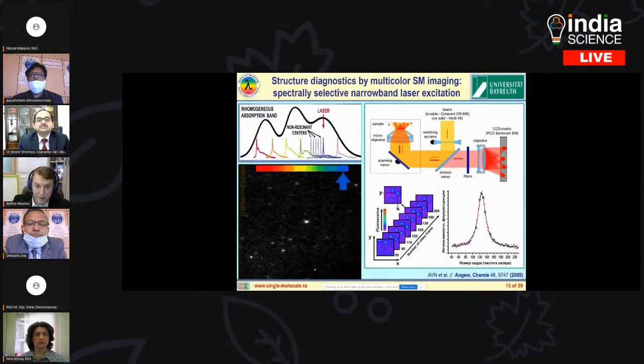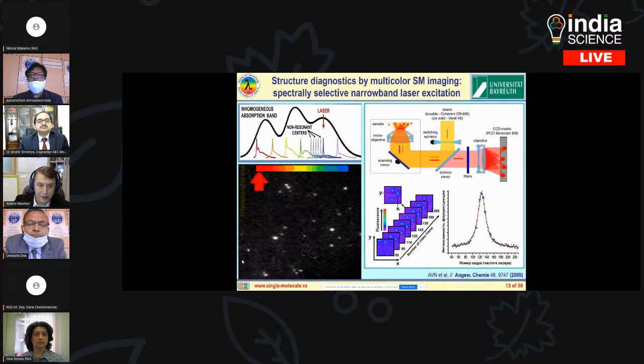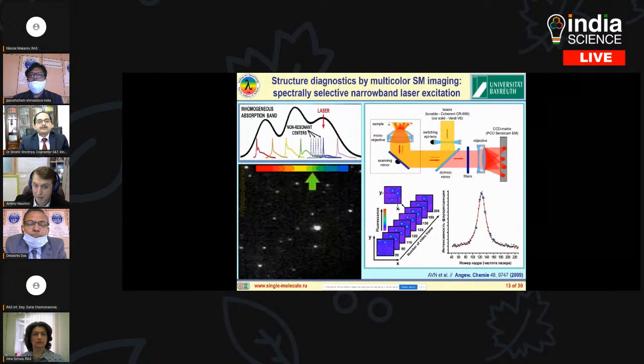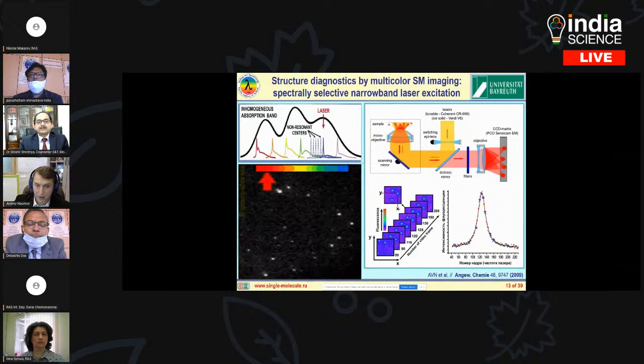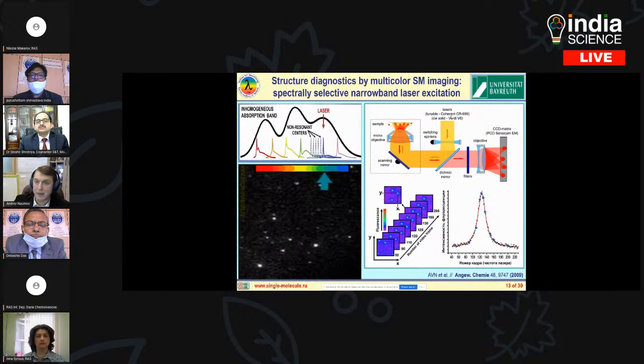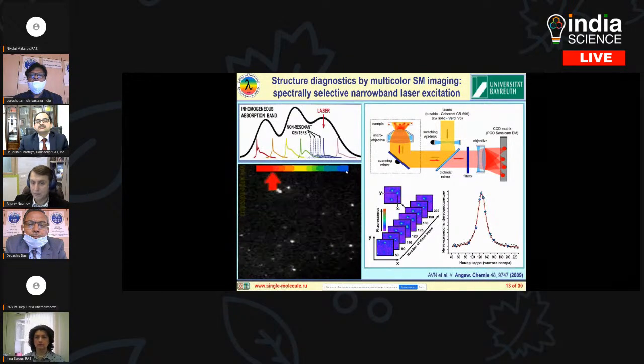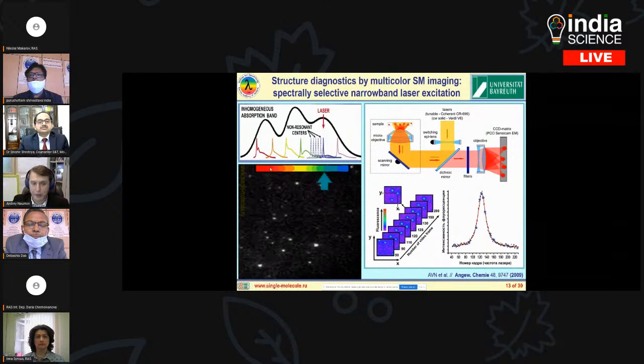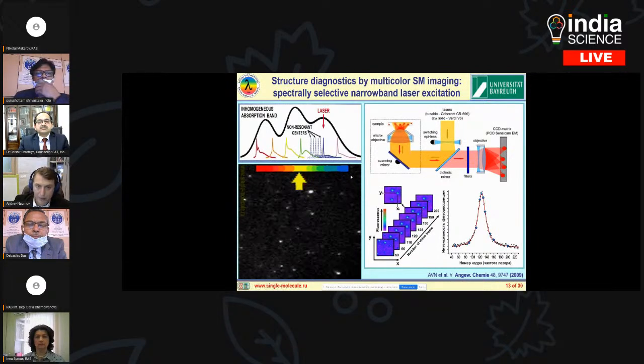This is my sample. It's a thin polymer film, about 50 micrometers. And I put inside of this film a lot of dye label molecules. And then I scan the laser excitation wavelengths, let's say, from blue to red. And you see, when the laser is in resonance with the electronic transition of a certain molecule, this molecule emits light.